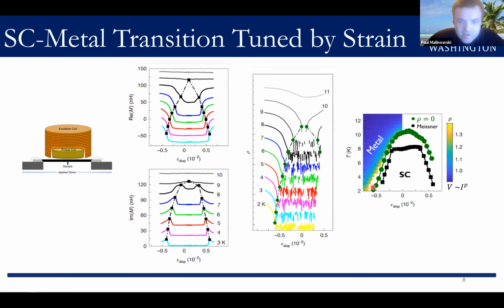So we can combine this data into a single strain temperature phase diagram, where the green circles mark the rho equals zero boundary, and the black squares mark the Meissner signature. And we see we have this dome-shaped phase boundary with a flat region corresponding to the detwinning region, and then these very steep sloped lines corresponding to the suppression. And this phase diagram also includes this color map, which gives the power of the sample's IV curve at that point. So blue is a value of 1, which gives linear ohmic behavior. And so what we see is that extrapolation of these phase boundaries to zero temperature imply that we can tune a superconductor to metal quantum phase transition as a function of applied strains on the order of 0.5%.